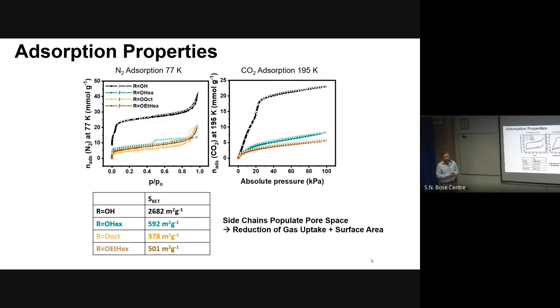We then looked at the accessibility of the pores by adsorption measurements. We did some nitrogen adsorption at 77K and some CO2 adsorption at 195K, and we can see that the materials that don't have any side chains take up more gas, which makes a lot of sense because we have more space and less weight in the material. It's normalized to the weight. From the analysis of the isotherms, using the BET method, the surface area is much lower if we attach the side chains. Interestingly, we also see some features of mesopores. This is a good sign that we induce some defects into the pore structure with the side chains present. Similar trends are observed for the CO2 adsorption at 195K.